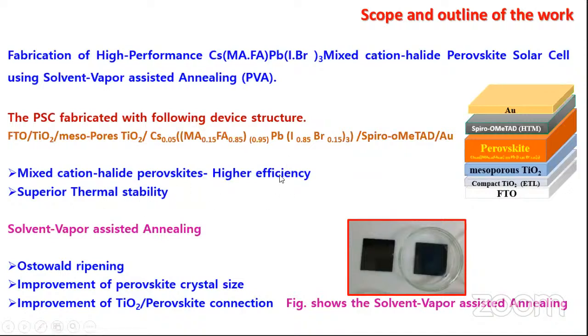Further, we need to increase the efficiency of this solar cell. We need to increase the perovskite crystal size by Ostwald ripening using the solvent vapor annealing method. This will improve the perovskite crystal size, and when the perovskite crystal increases, there is a good connection between the TiO2 and the perovskite.